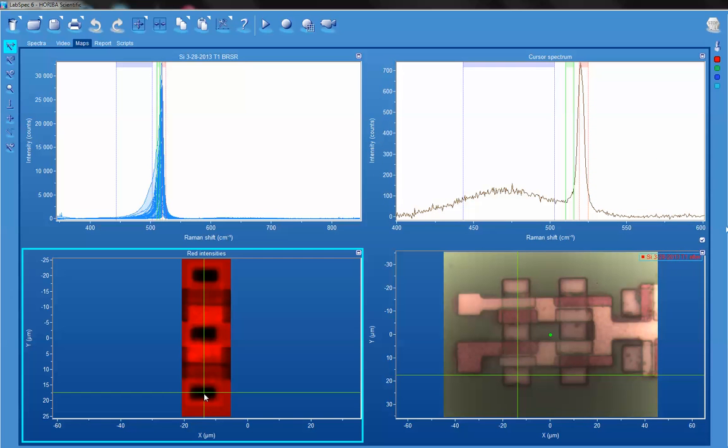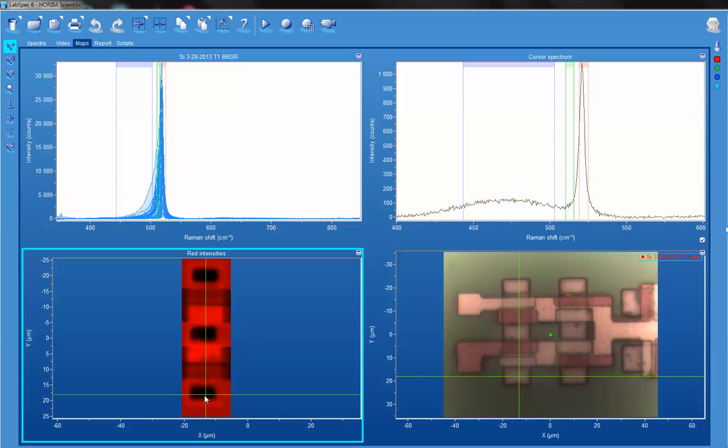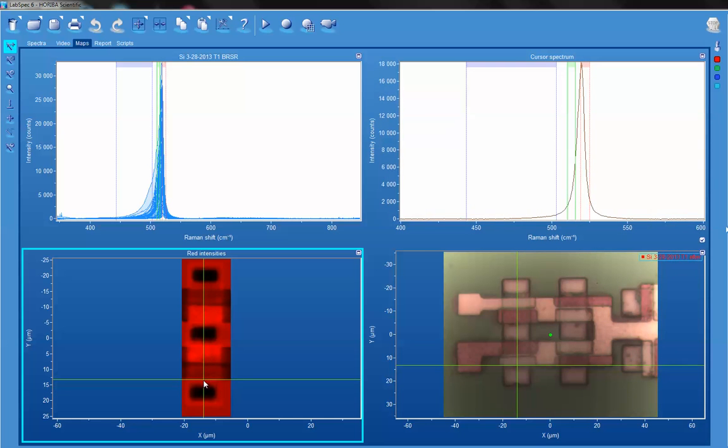And as a result of that, the intensity of the first order phonon mode from the Brillouin zone center is significantly reduced. And then you also see this Raman scattering from the amorphized portion of the silicon. So when an implant occurs, it basically disrupts the long-range translational symmetry, and so you have a major decrease in the Raman scattering strength.